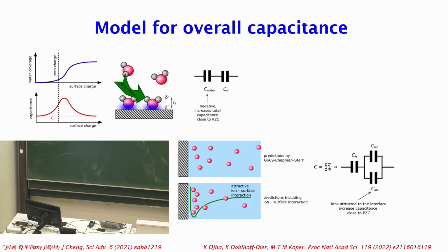That still doesn't tell us why we have this relatively weak electrostatic interaction. There's now a paper in the literature. We already suggested that maybe it's an image interaction that is weak enough. You wouldn't expect that image interaction if water has the dielectric constant that it has in the bulk, because then that image interaction would really be too weak. But if the dielectric constant near the surface is lower, then the image interaction becomes stronger. And maybe that explains why we have this. And maybe then this image interaction is different between platinum and mercury, which is maybe not so unreasonable.